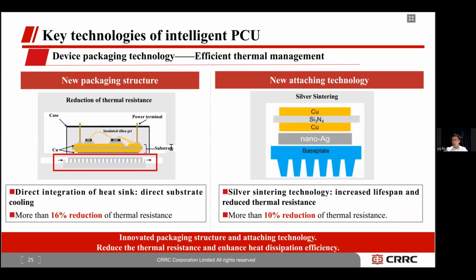As the power device was integrated with the heatsink, the chips would be cooled directly without a base plate, which contributed to a further 16% reduction of thermal resistance. We implemented silver sintering technology, which would enhance the lifespan and reduce the thermal resistance by at least 10%. Such innovative packaging structure and welding technology lead to a reduction of thermal resistance and an improvement in heat dissipation efficiency.